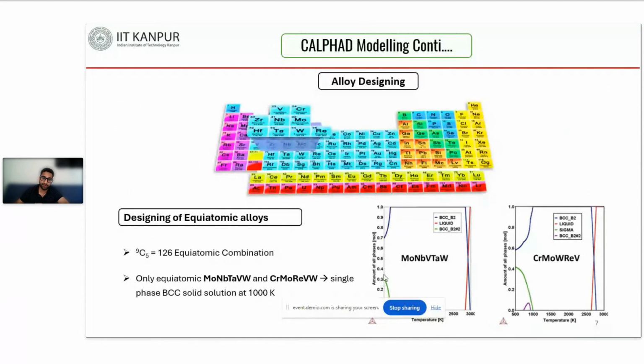In this, what we have done in the high entropy alloy design concept is we have taken 9 elements, and all of these are refractory metals. From these 9 refractory metals, we have selected 5 metals at a time, because we want to make a quinary alloy, and initially we take all the principal elements in equiatomic composition. That means their chemical compositions are in equal proportion. From the 9 refractory metals we develop a quinary alloy by selecting 5, so it becomes 9C5, which is equal to 126 equiatomic combinations.